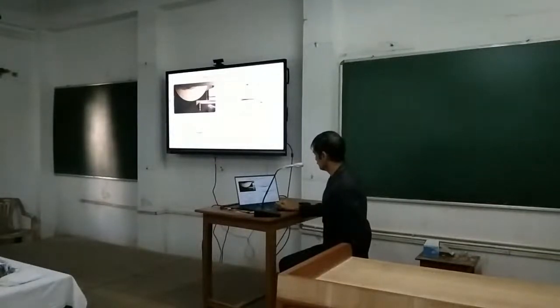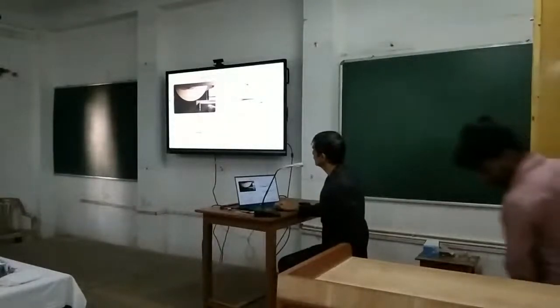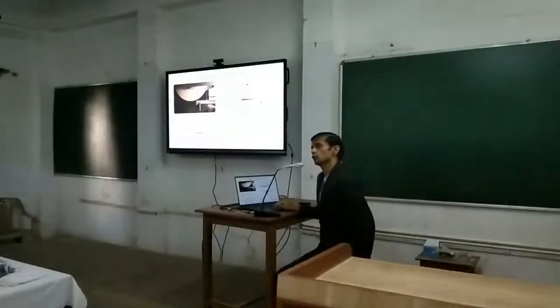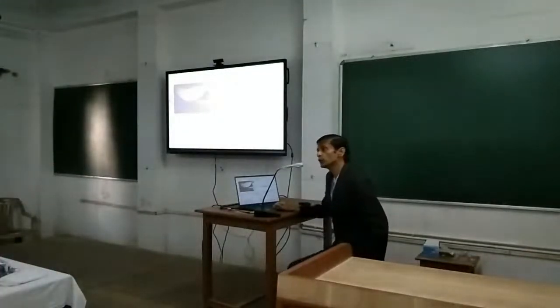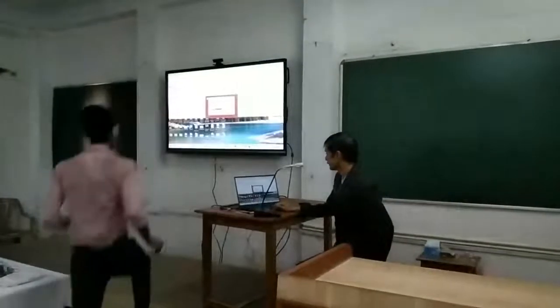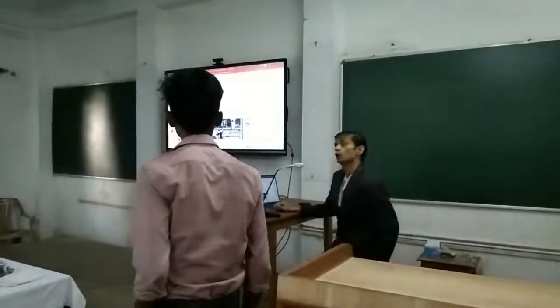A is the depth of cut of the downfeed and D is the equivalent diameter of the wheel. So anyway, here it is the diameter of the wheel. This particular value comes down to the order of microns. Although you are giving a depth of cut of 40 microns, the grit penetration depth comes back to the order of only 2 to 3 microns.